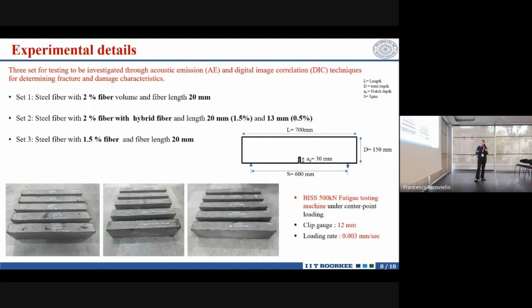So now, in order to see the fracture properties and the fracture behavior, we have casted beams in 3 different categories to study the post-cracking behavior under fracture. In the first set we have used 2% fiber with 20 mm length, and in the second set we have used 2% fiber but with a hybrid combination of 1.5% 20 mm fiber and 0.5% 13 mm fiber. And in the third set we have used 1.5% with 20 mm fiber, and this is the cross section that we have used for the beam for flexure testing.